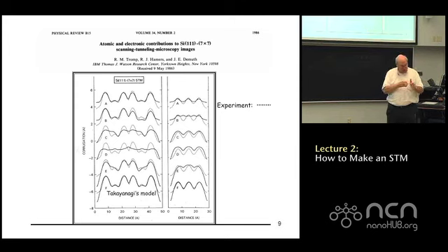So these are along certain distances of that silicon 111 surface, right? And the bumps in that solid line are the predictions of these different models of where the atoms are going to be located. Once Binnig and Rohrer do the STM image, they know exactly where the atoms are located along these high symmetry directions. Where the atoms are located are indicated by the dashed lines. And what you see is, of these 6 theoretical models that were presented, there's only one, Takayanagi's model at the bottom, where the fit between experiment and theory is right on.